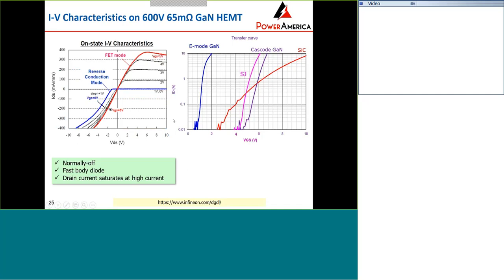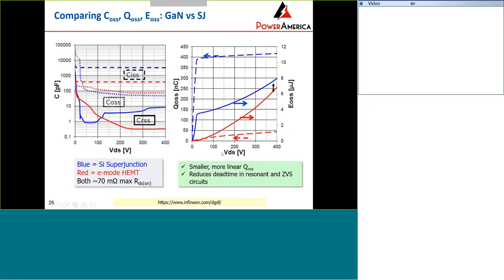Only one aspect needs to be improved for the gallium nitride E-HEMT, which is the threshold voltage. This figure compares the different transfer curves among the GaN HEMT, cascode gallium nitride HEMT, superjunction, and silicon carbide MOSFET. You can see that the E-mode gallium nitride has the lowest threshold voltage compared to other devices. So for power applications, it is probably desirable to have a higher threshold voltage for the E-mode gallium nitride in the future. Another advantage of gallium nitride devices, if you compare with silicon superjunction, is that it has lower or similar resistance at similar blocking voltage.